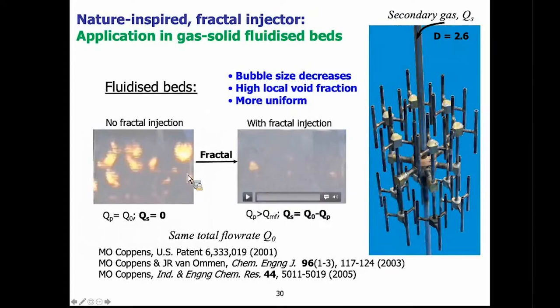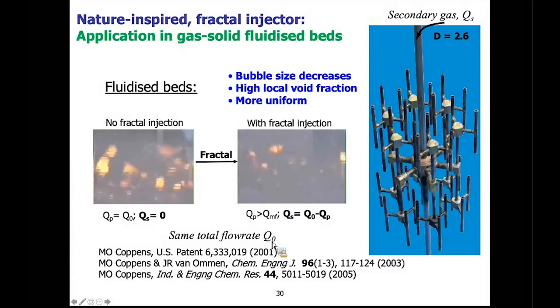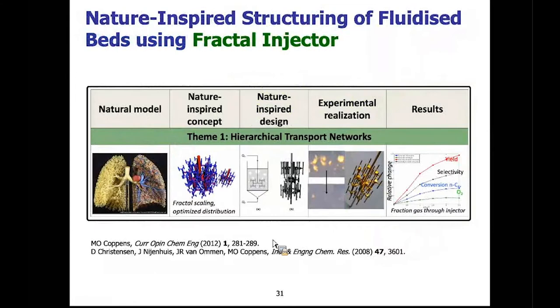Okay? And so typically, the bubbles that are formed in there become very large and they start coalescing and growing. And so it is quite difficult to scale these systems up. All right. And so you see these kind of flame-like bubbles when you look through. Now, when you use this fractal injector to have some of the gas going through, look what happens. So these gas bubbles become much smaller. They're much more uniform because the gas is immediately, intimately within the vessel contacted with a solid. So when you apply this, you have a much better contact. And so you have much more efficient reactors.